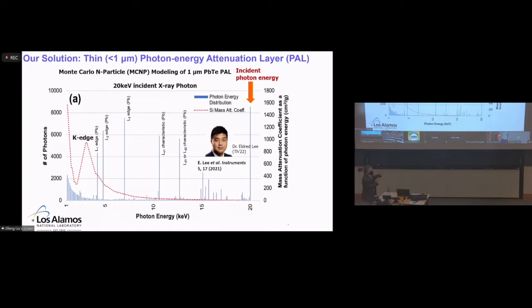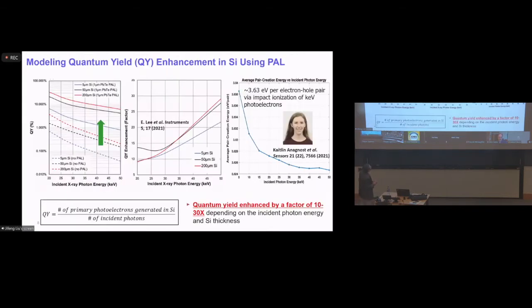You know, with this PAL, you can actually reduce down the photon energy. You can convert many of those photons to low energy in a range between 1 kilo electron volt and 5 kilo electron volts. And that matches the absorption capability of silicon much better. But here you have more absorption coefficient from the silicon. So that's essentially the idea of this down conversion process.